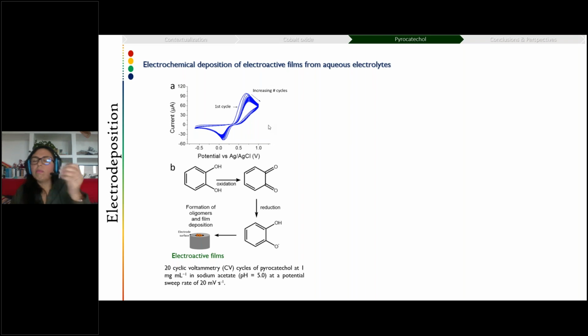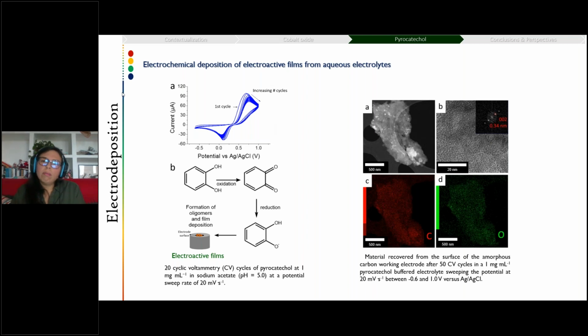And we observed, when we scratched the surface of the electrode, that we were able to recover some grains of this electrode deposition film. And we found that all of it was formed of carbon and oxygen, but there were some patches with different contrast from the rest. And there were some regions that were definitely crystalline, meaning that we are forming something composed only of carbon and oxygen that has a crystalline structure. So we wanted to see what was happening. This was an indication that probably we are forming a graphitic structure, and we wanted to test this idea.